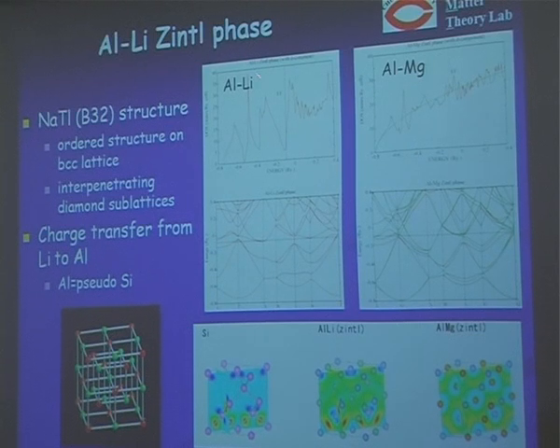But if we replace the lithium with magnesium, the electronic structure changes completely. This is the result, and the density of state looks like a nearly free electron density of state. And if you look at the band dispersion, the band dispersion is also almost the same as the free electrons. So that means in the aluminum-lithium case, this one is almost a semiconducting system. But this one is a nearly free electron metal.